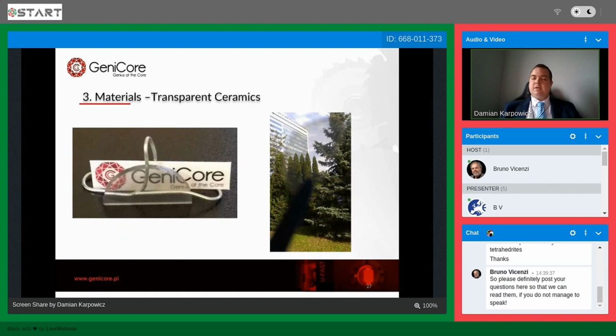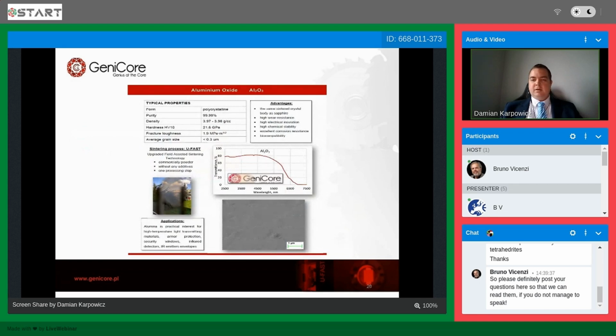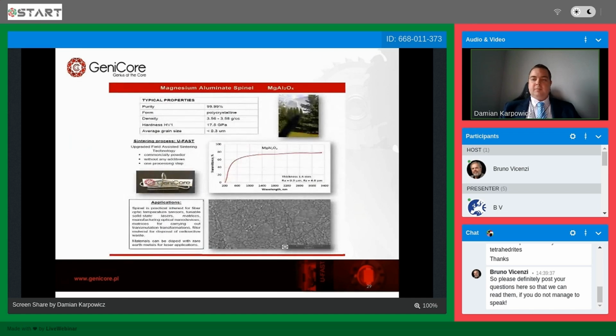Transparent ceramic has a lot of applications where it can be used. We specifically had a chance to produce the covers for missiles. So infrared and guided missiles need to have covers on the top. So basically, transparent ceramic can be used there. However, there are some challenges related to the shapes when it comes to this application. Nevertheless, the idea was to show that you can produce with SPS technology fully transparent ceramic with commercially available powders without any additives. So no lithium, nothing, just the commercially purchased powder. And with one processing step, we are able to achieve the transparent ceramic.